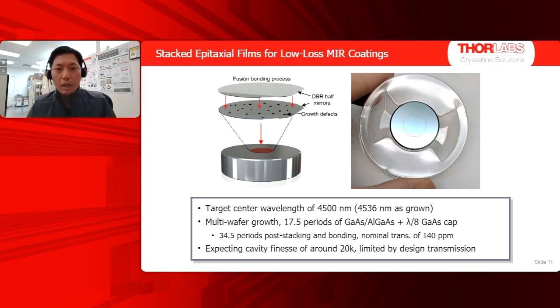So then how do we actually grow and make these crystalline mid-infrared mirrors? Well, the naive approach would simply be to grow the entire stack that we need in a single MBE growth and transfer them onto an optical substrate, kind of the way I schematically talked about a couple of slides ago. The thinnest multi-layer that you can achieve is a quarter wave stack.